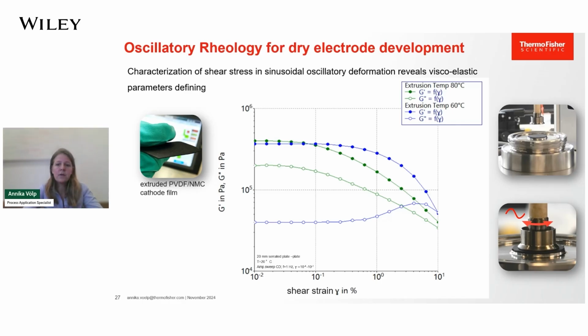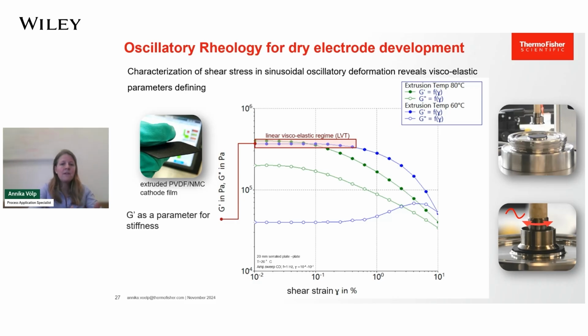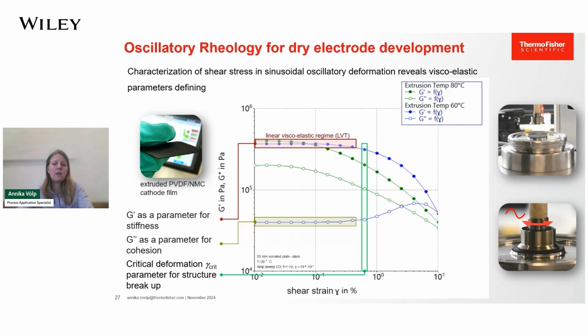The plot on this slide shows the viscoelastic properties of dry electrode material produced under different conditions. The information that can be extracted from this experiment includes the storage modulus, G prime, which is a constant value at low strain values in the linear viscoelastic regime, and it serves as a parameter for the stiffness. The loss modulus, G double prime, in the linear viscoelastic range, serves as a parameter for the cohesion inside the sample. The critical deformation at the end of the linear viscoelastic range indicates structure breakup and is a parameter for the stability of the sample.